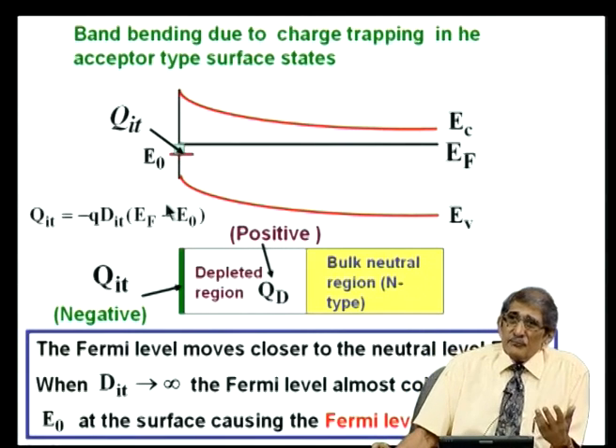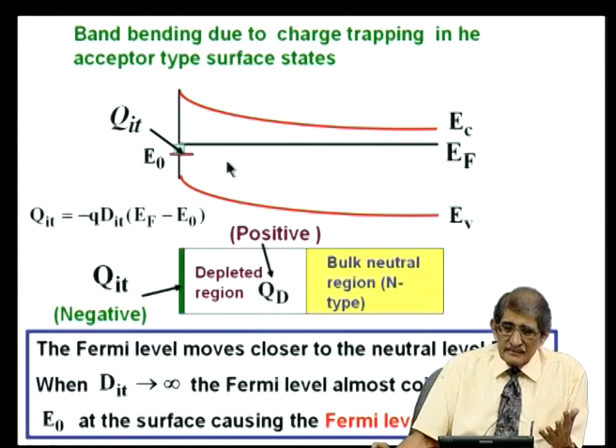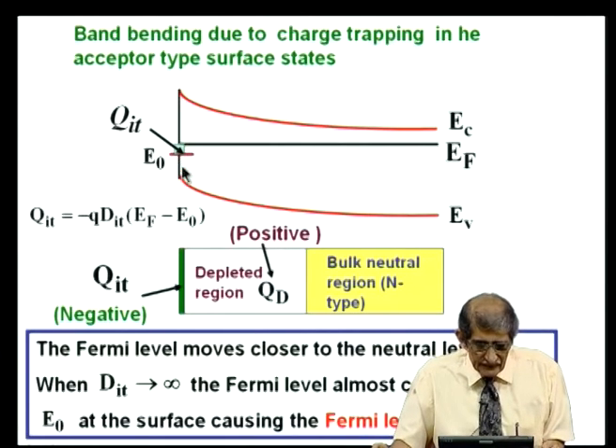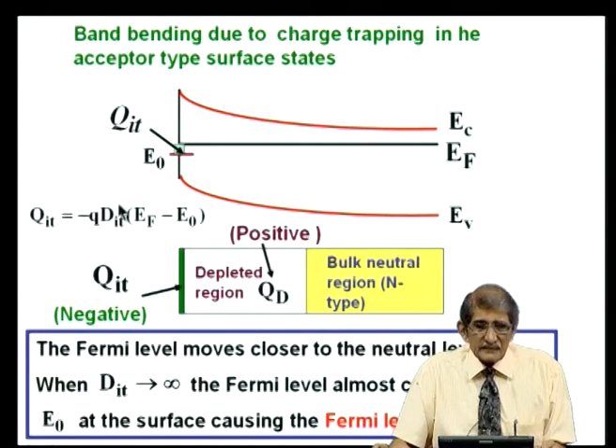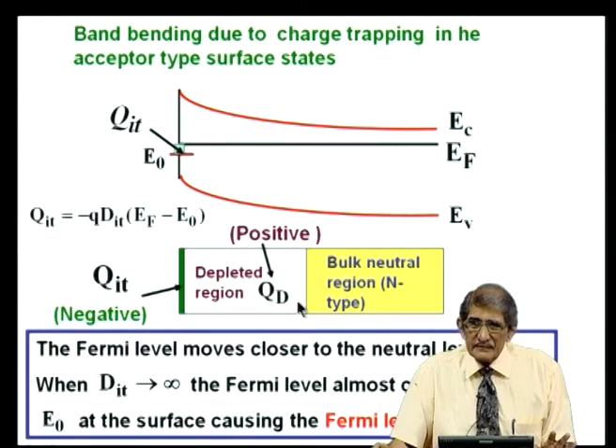So, here you can see, even if you do not put the metal there, the electron transfer has taken place and the Fermi level is getting closer and closer to this neutral level E naught. The charge in the interface for a free surface is equal to Q into dIt, where dIt is per centimeter square per electron volt. So, the number of acceptors present between E f and E naught is E f minus E naught into dIt. The charge is negative there, which is minus Q dIt into E f minus E naught. That charge has come from this depletion layer. So, Q it in magnitude is equal to the Q d in the depletion layer, which is Q N d into W, where W is the depletion layer width.